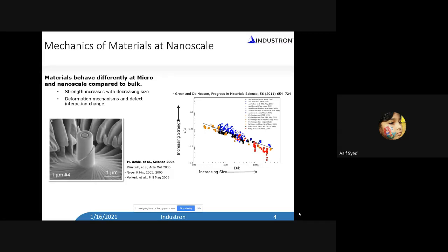That is known. But around 2002, 2003, a group of scientists at the Army Research Lab took samples, and they FIB'd them. You can make the samples very small when you FIB in a SEM. And they made pillars, basically, and then they started compressing those pillars. And they started to see a tendency, as you reduce the size of these pillars smaller and smaller, that yield strength basically increases as you reduce the size of the specimens.